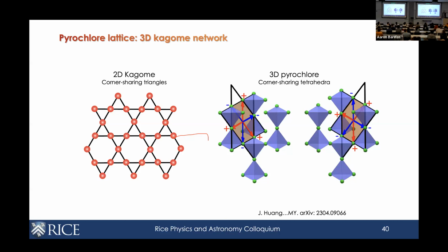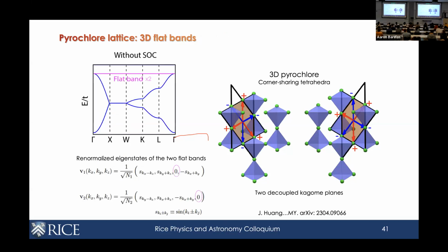So everything we know about Kagome lattice is still valid in the in-plane direction. But if you actually think about the out-of-plane hopping and calculate your Wannier amplitude, you will see that the atomic lattice that is actually not contained within this layer has identically 0 amplitude. What does that mean? That means that the electrons cannot hop outside of this between the layers. And this means effectively we have a picture where you can consider the pyrochlore lattice as 2 decoupled Kagome planes. And everything we have learned about Kagome lattice still carries over in the formation of these flat bands.